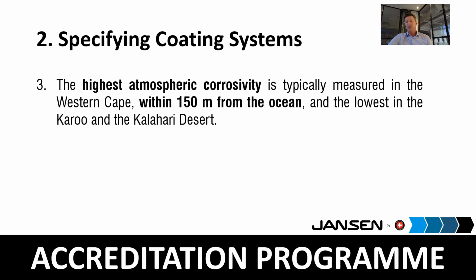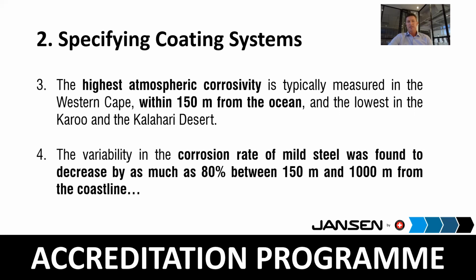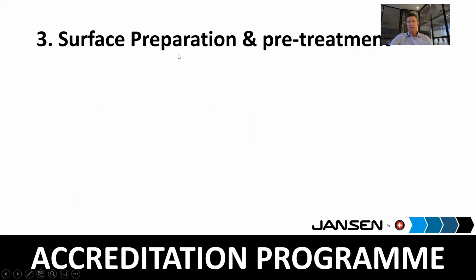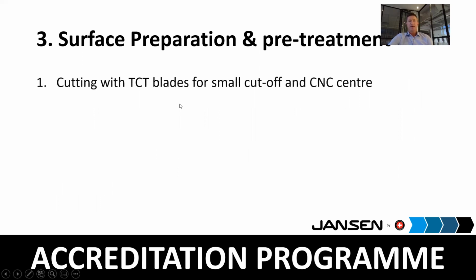The highest atmospheric corrosivity is typically measured in the Western Cape within 150 meters from the ocean, and the lowest in the Karoo and the Kalahari Desert. And lastly, the variability in the corrosion rate of mild steel was found to decrease by as much as 80% between 150 and 1,000 meters from the coastline. So that is very significant: a kilometer in from the coastline, there's a reduction of as much as 80% in terms of corrosivity. All right, let's look at number 3, surface preparation and pre-treatment.